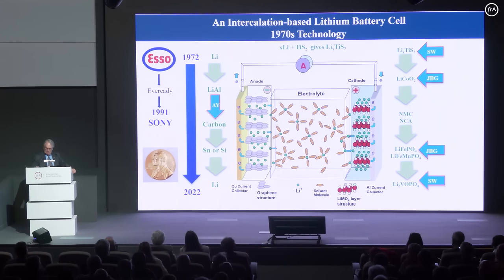And I should point out here that what you see here is what we call intercalation compounds. What this means is you insert some guest species into a host lattice, and you can see in here the lithium ions are little green circles. And on the left-hand side is that graphite. It's a layered sheet, and if you've got old pencils, that's graphite that you're putting on your piece of paper.